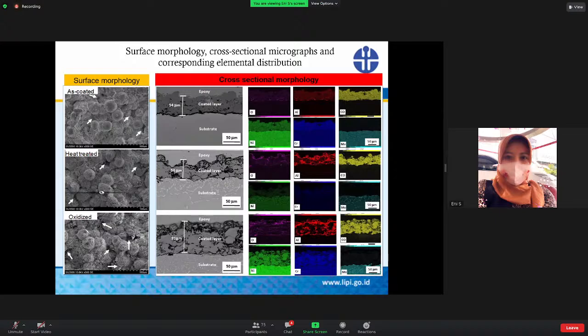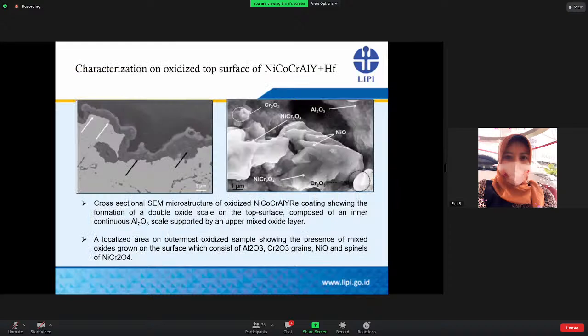It is worth noticing that a longer exposure time for the oxidation test is required to obtain a thin and stable oxide scale formation on the coated samples. Therefore, characterization of the oxide top surface of these coated samples was performed in order to understand the properties